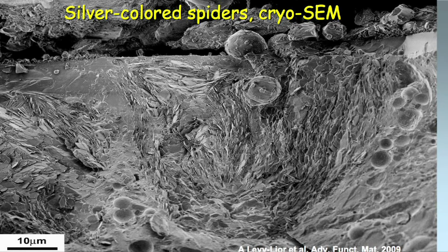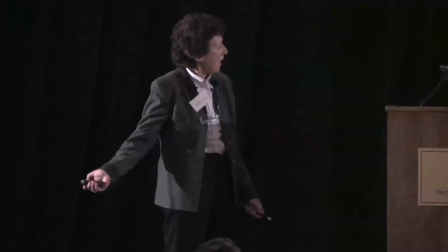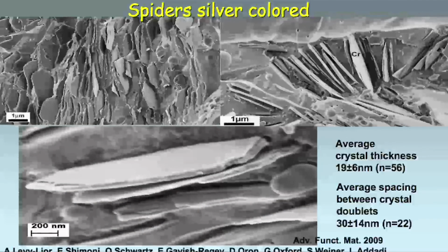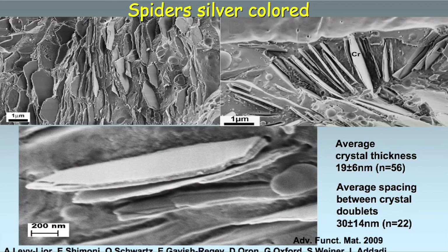When we look at the cryo-SEM, now it looks much more messy. Here, I hope that you see the thin crystals as we saw in the fish. But in the fish, it was a fantastically, periodically ordered system. Here, it's not. We have all kinds of orientations of the crystals. But there is a short-range order. There is a certain persistence in the short range. And then, when we looked at the crystals at high magnification, they are indeed all doublets. They are doublets of crystals with a material in the middle that does not evaporate when we etch. So this is a solid material. This doesn't look like water.